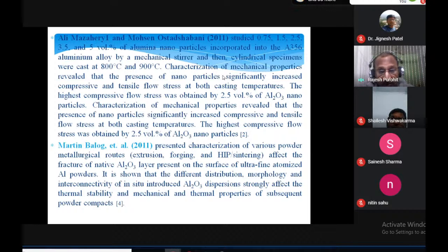And characterization of the mechanical property revealed that the presence of nanoparticles significantly increases the compressive and tensile flow stress at both casting temperature. The highest compressive flow stress was obtained by 2.5 volume percent of nano alumina particles, as I told earlier also. About 2.5 to 3 we get better properties. Usually effect of casting temperature are also studied here, two different casting temperature, 800 and 900. The highest compressive flow stress was obtained by 2.5 volume percent of nano alumina particles.